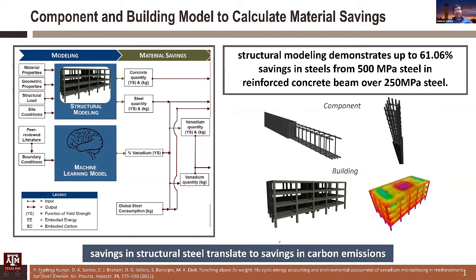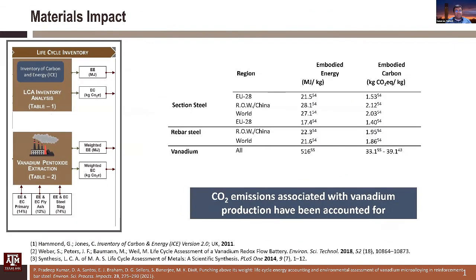And we can figure out the savings in structural steel in terms of vanadium microalloying. One of the things that we find from here is that we get about 61% savings in steel from using 500 megapascal steel in rebar as compared to 250 megapascal steel. This is pretty large, because by using 500 MPa steel, you can design the building very differently and still have the same load-bearing properties and seismic resilience, but use much less steel and much less rebar, and that can translate to significant savings in carbon emissions.